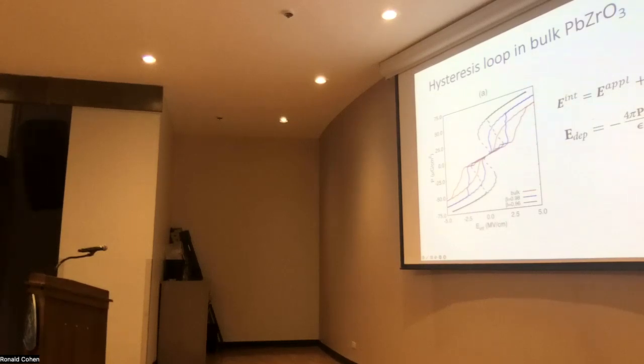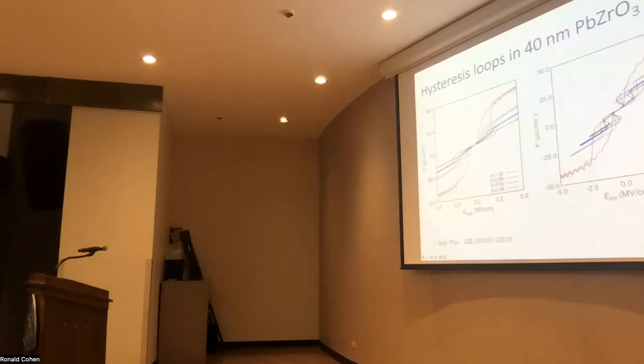This is just motivation. It suggests that we could in principle look for that negative capacitance regime, but we have to consider depolarizing field. So that motivates us to look into films, because as we all know, films have a lot of depolarizing field. That is a good place to start. So we turn to the film simulations, and here we simulate 40 nanometer lead zirconate film.